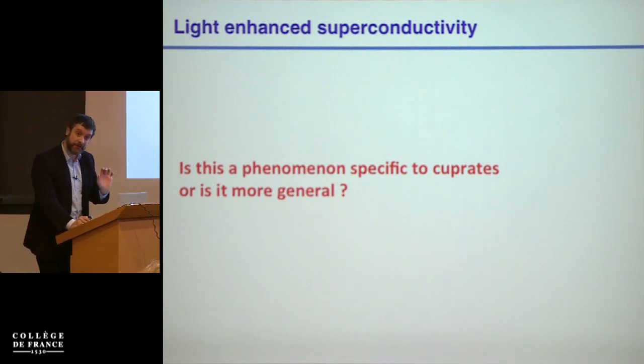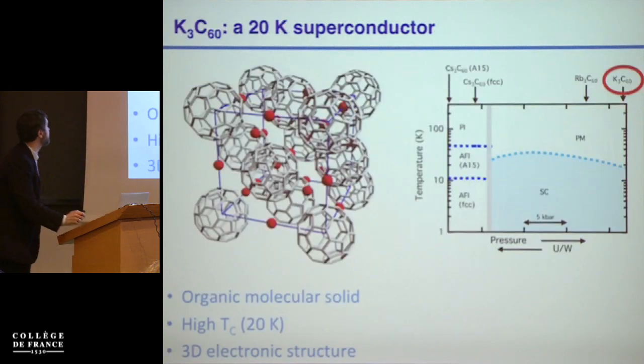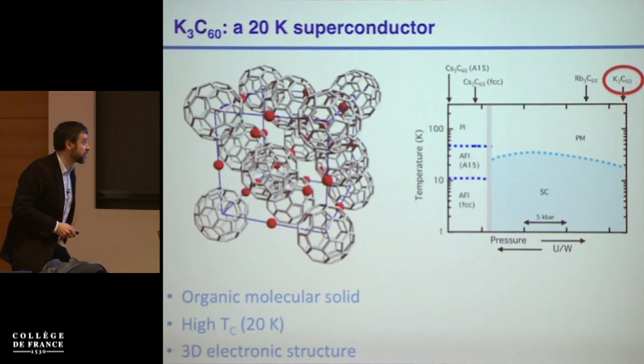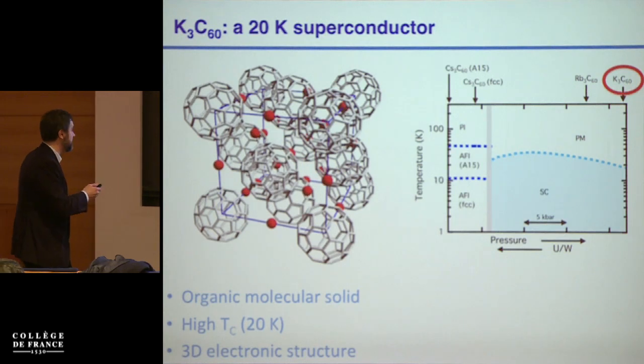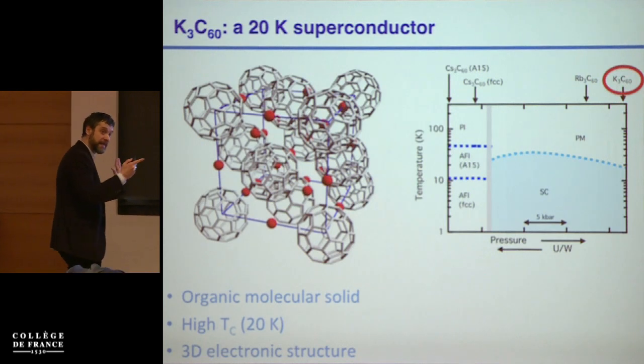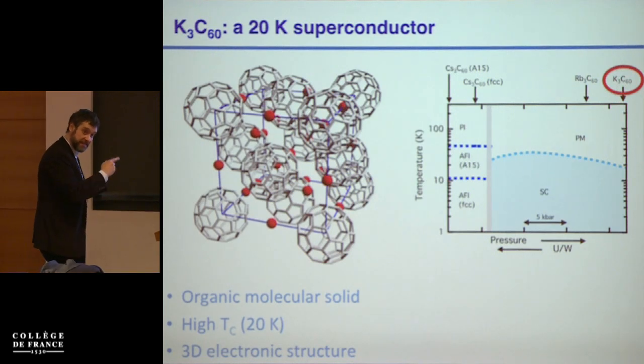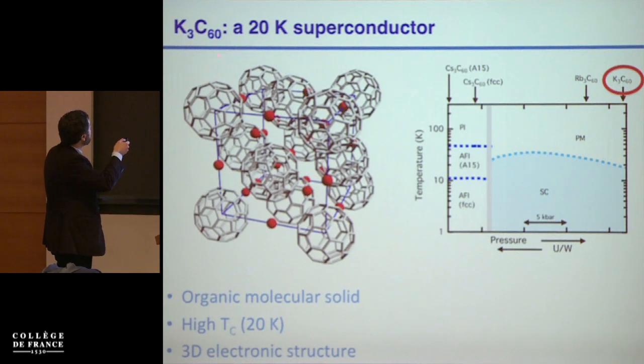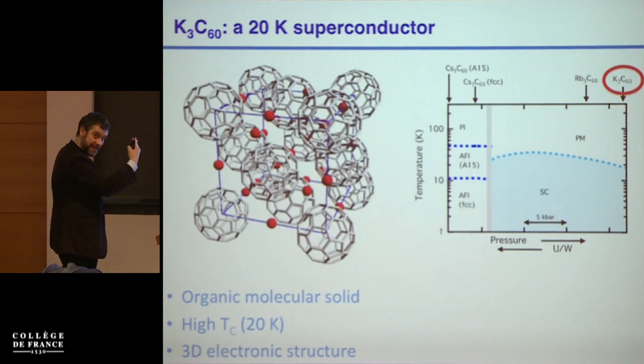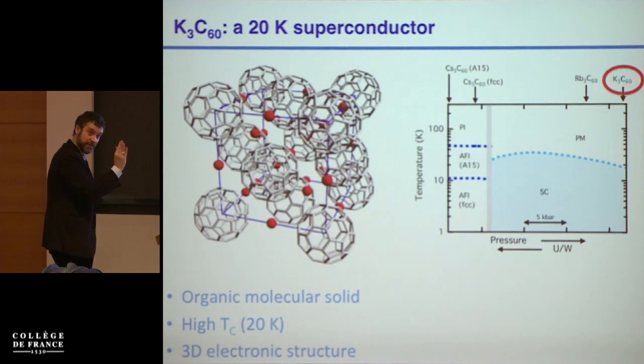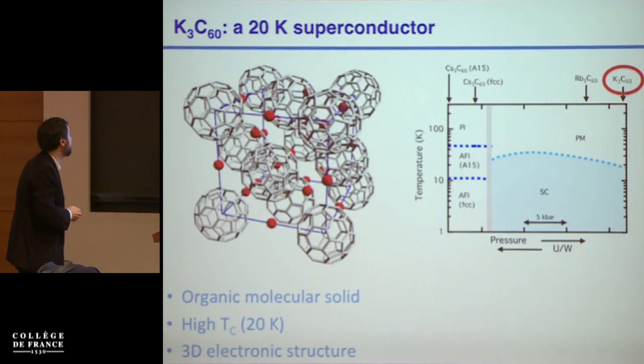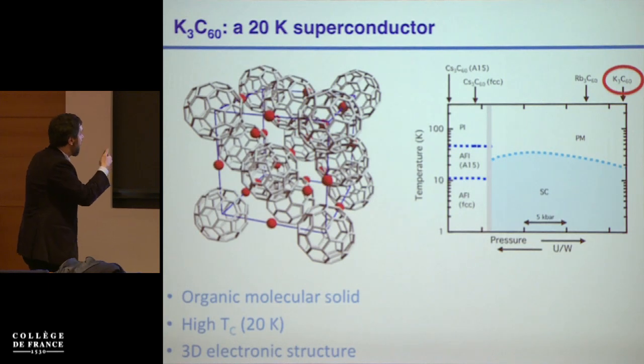But one in principle can take materials in which one has very strong optical phonons that are very different from cuprates, and nevertheless one could do a similar experiment. So another material that we've focused on, and this is really something only for the next 10 minutes, is this potassium 3C60 superconductor. This is one of a family of doped fullerite superconductors. In this particular case, this is not the highest temperature superconductor. The cesium material is more correlated, and under pressure has a 40 Kelvin transition temperature. But in this case, at ambient pressure, one has a 20 Kelvin superconductor.